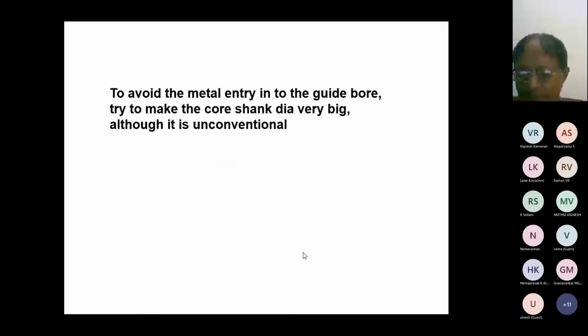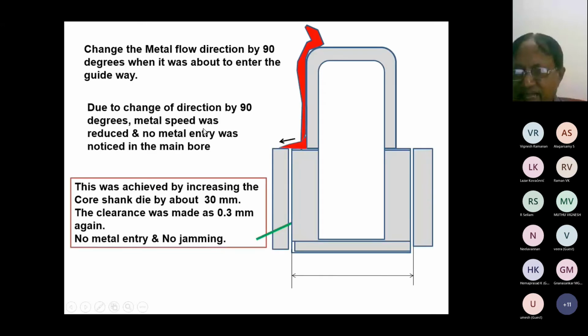So what we thought is, why not make the core shank bigger? Like this, something new idea, which is normally not done. This is an unconventional way of making the die. We have made this core shank 30 mm more than the previous diameter. So when the metal comes over here, it will not go here. It will get the pressure and get diverted by about 90 degrees. By that, the speed is reduced. Surprisingly, we found there is no metal entry at all.